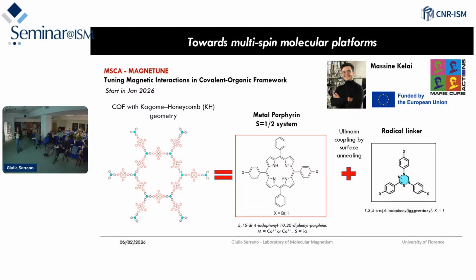And then we have to activate the Ullmann coupling between this Verdazyl compound and the porphyrin units. And in my opinion, the most challenging task will be to really create a homogeneous layer, because we could also have cross coupling with homo coupling, so we can couple the same species. We are now planning to use different halogens, but for sure we will start from the deposition of both compounds. We are going to study first this species, then this other.